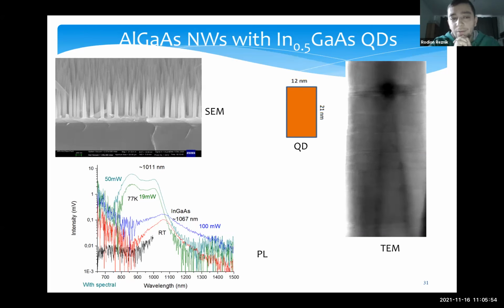So we have grown these nanostructures. You can see the SEM. It looks like usual aluminum gallium arsenide nanowires on silicon, and then you can see the TEM of this strained nanostructure. So this is the quantum dot. This is again the indium gallium arsenide quantum well. For us, maybe a parasitic quantum well, but let's see. In this case, we have again room temperature PL spectra from these nanostructures, from aluminum gallium arsenide somewhere here, but here from indium gallium arsenide. This is the PL spectra at 77 Kelvin.